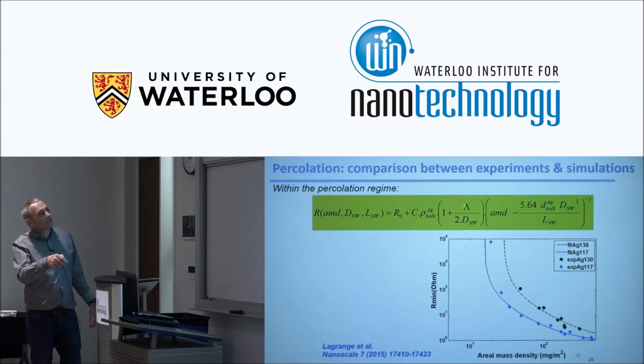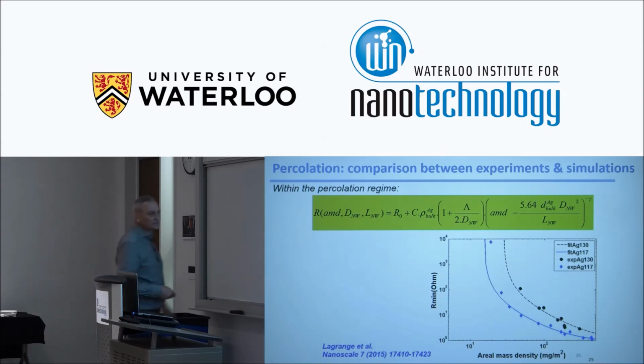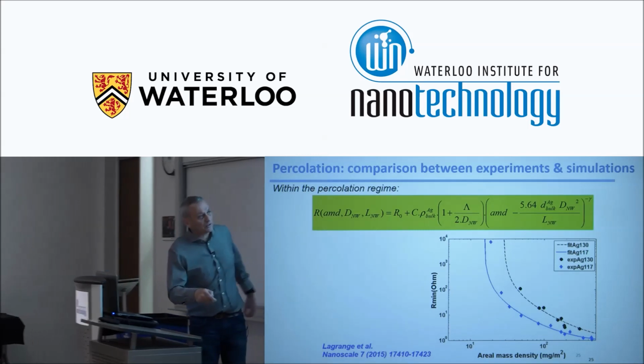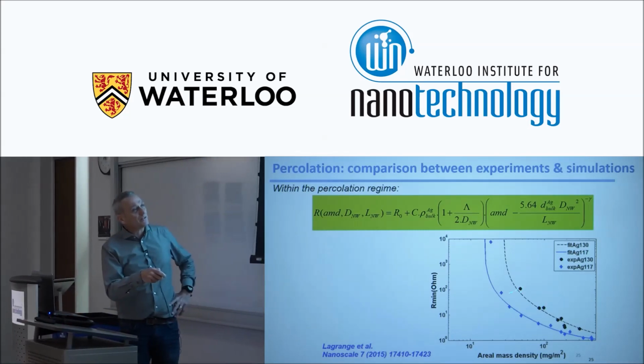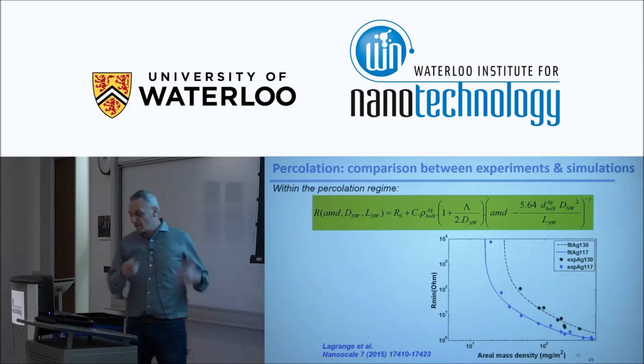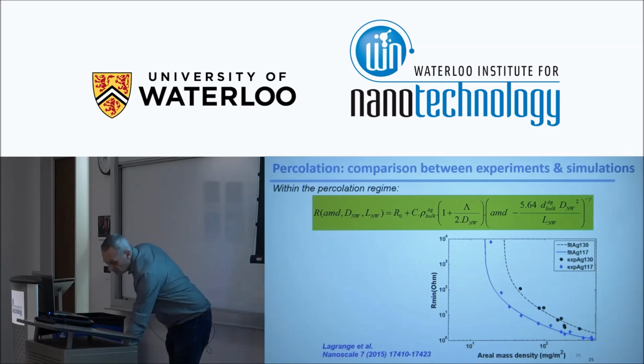We know the mean free path of electrons in the silver. We know the diameter. The AMD that we are going to measure minus this, and we know everything here. So we can use it to fit the symbols, the experimental data. This is the minimum resistance we observed during a thermal ramp in log scale versus the areal mass density in log scale. And the different points correspond to different nanowires, 117 nanometers in diameter, 130 nanometers in diameter, for 2 sets of nanowires as well coming from Seashell Technology.